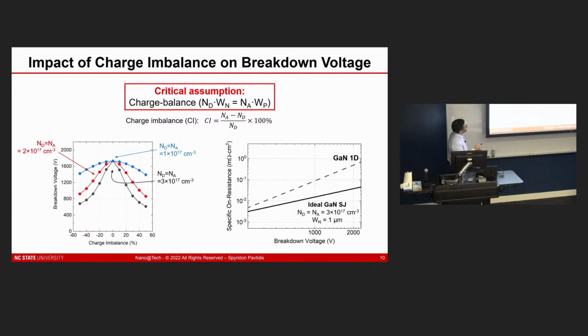And the other really important thing to keep in mind here is that that slope, or that roll-off, is very dependent on the doping level that you're using. I mentioned earlier I want to have a high doping level to reduce my losses, but you can see here that now puts me in a very risky position. The higher doping I'm using, the more aggressive that roll-off becomes as well. So the need for charge balance becomes even more important.